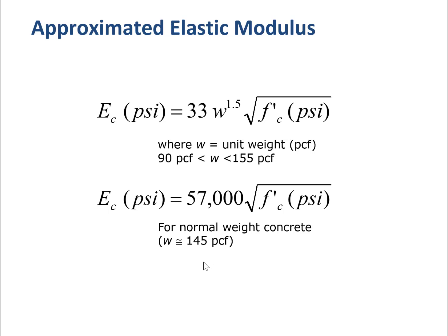Actually, there is a more general formula, which is this one. It shows that the elastic modulus Ec equals 33 times W to the power of 1.5 times the square root of fc. So fc is the compressive strength, Ec is the elastic modulus, and W is the unit weight of concrete. It can be somewhere between 90 pound-force per cubic foot to 155 pound-force per cubic foot. If W is approximately equal to 145 pound-force per cubic foot, then you can directly use this formula.